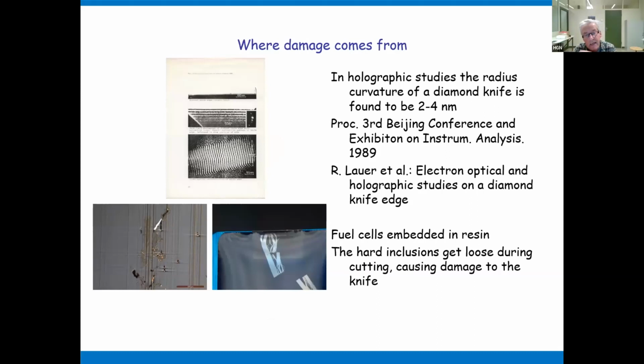You see the radius curvature, and then the image left down. You see a sample surface of a sample which had some fairly brittle material, a fuel cell embedded in resin. And it's not the hardness of the fuel cell, it is the sample is pulled out, the small fragments are pulled out during the cutting process, and this causes the damage.